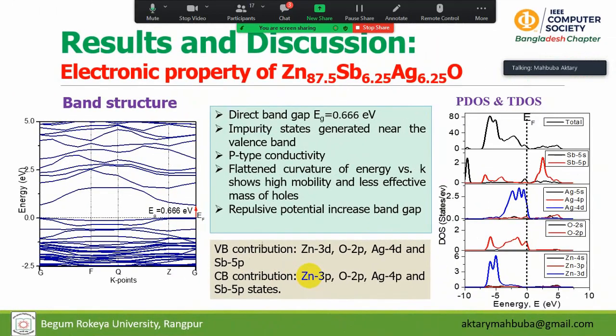Electronic property of silver, antimony co-doped zinc oxide. Here we can also see a band structure and direct band gap with energy 0.666 electron volt, and here impurity states also generated near the valence band, and which is also a strong evidence of p-type conductivity. The flattened curvature of the energy versus K diagram shows the high mobility and less effective mass of holes, which is actually resulted from repulsive potential increased to increase the band gap.